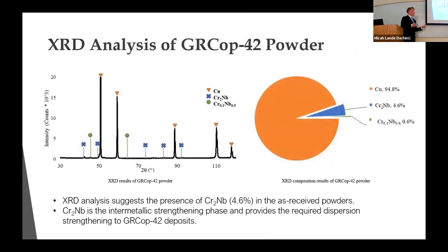So then moving over to some of the characterization, beginning with Cu-Cr-Nb (GRCop-42), taking it to do some X-ray diffraction. We can see that the majority of it is just pure copper, exactly where we expect it to be. We can see our secondary phase, which is that chromium and niobium alloy, which is, again, exactly where we expect it to be. And then we did also find something that I wasn't expecting, which is a third phase here, a different ratio of that chromium niobium mixture, but that's such a small amount, we're not too worried about that. So again, we have that secondary phase, which shows that this is going to be good for creating solid intermetallic bonds.